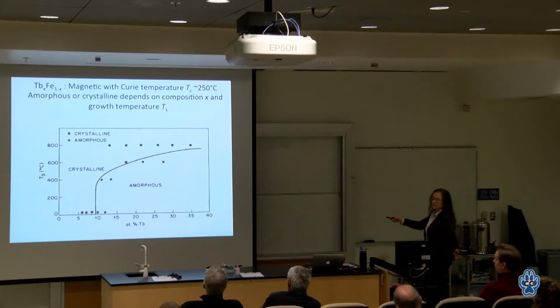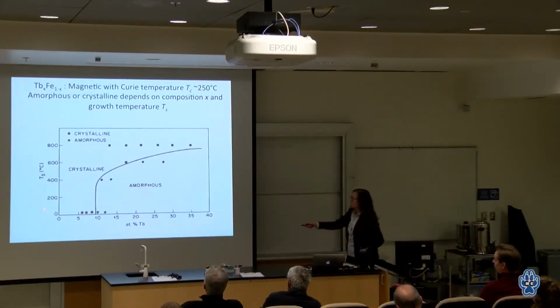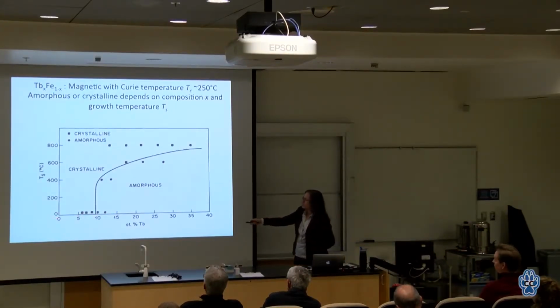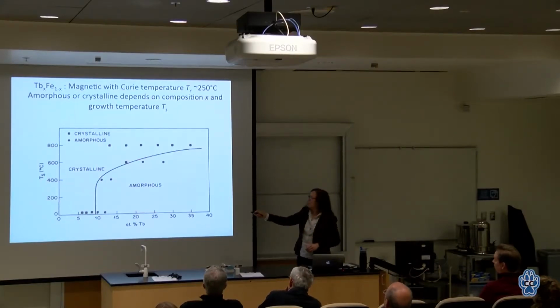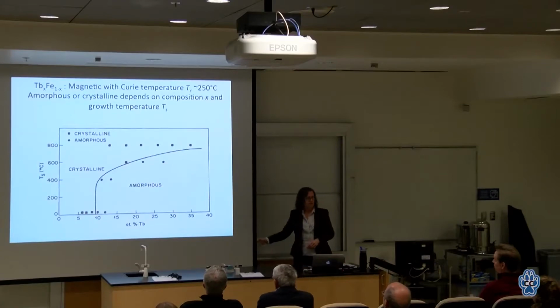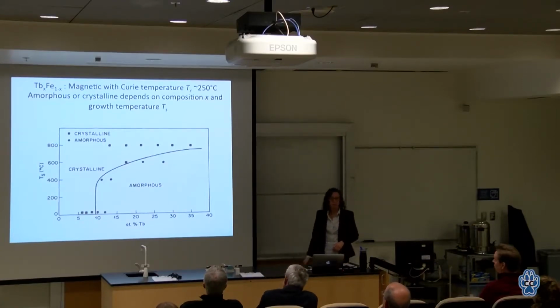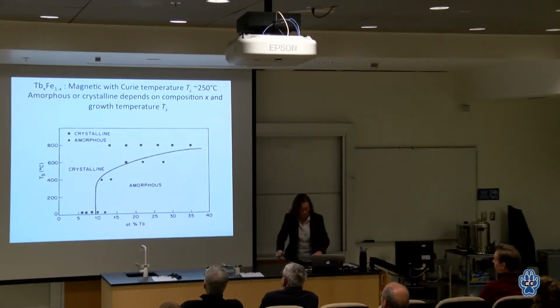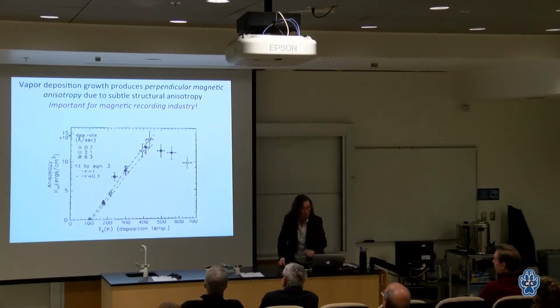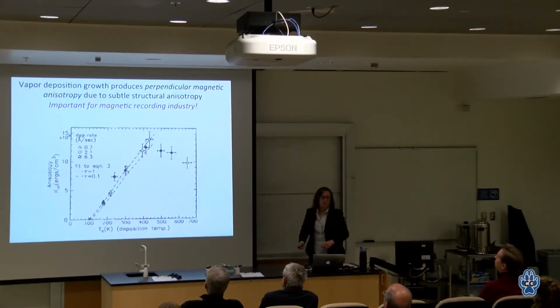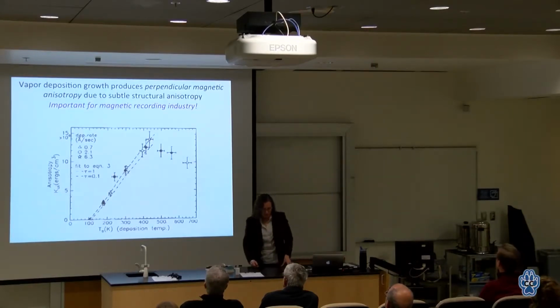And this is sort of a phase diagram of that. So if I grow at low concentrations of terbium, it ends up crystalline. As I go to higher, more and more terbium, I get to a whole region where it ends up amorphous. As I grow at higher temperatures, it ends up crystalline. But you can see there's a fair amount of phase space in here where I can make amorphous terbium iron. So, okay, well, that's fine. It's magnetic. The thing that is interesting about it is it's anisotropic.